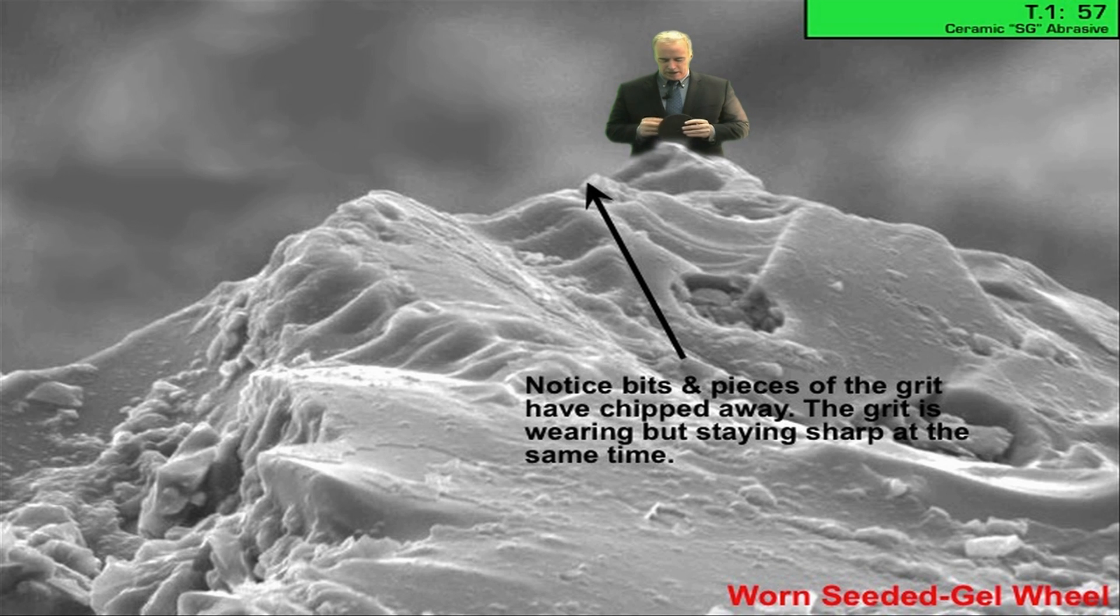So if we're going to get that guy to fracture in little pieces, which is the way we've designed this, we're going to have to beat on him pretty hard because he's so tough. If we don't beat on him hard, he's just going to become dull and generate a lot of heat.